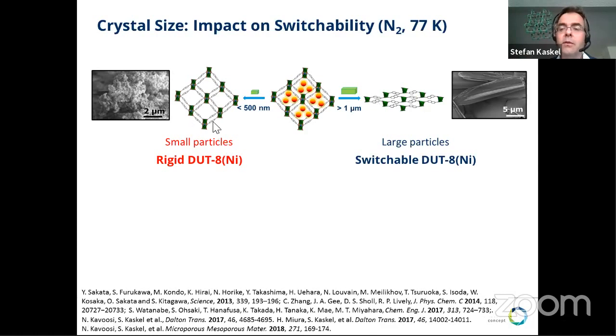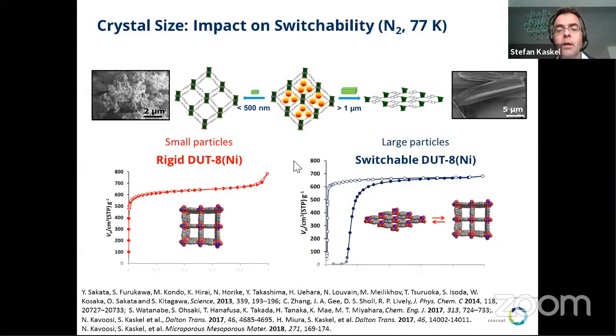And so this network here remains rigid, although it has the same chemical composition as the large particles here. And this we call switchable. In a second, you can see that there are significant influences on the adsorption behavior. The rigid one shows a typical type 1 behavior, no switchability, no gating, no switching. And the switchable variant with the same chemical composition, but only larger crystals, shows the switchability. So it switches open here in nitrogen adsorption at about 0.1 in P over P0.